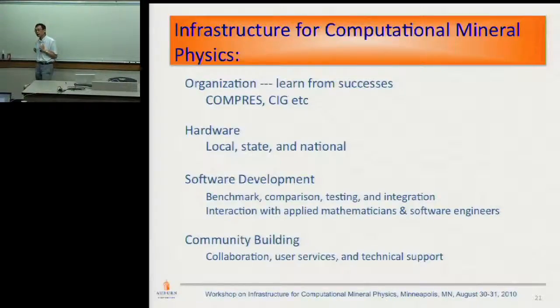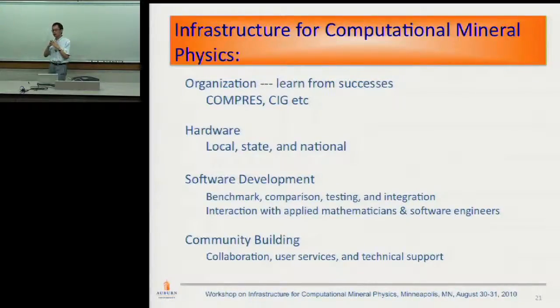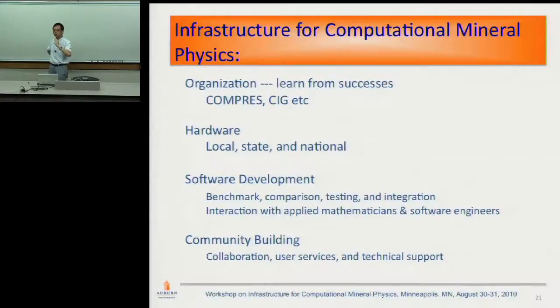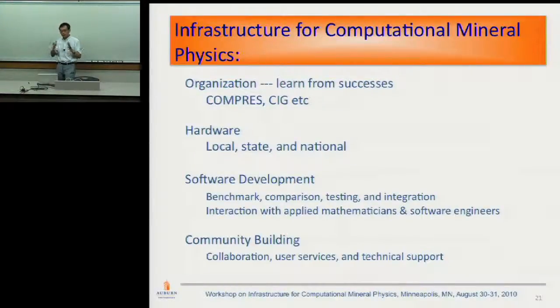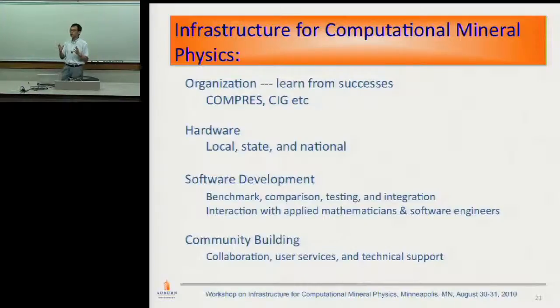We only had one paper on the conductivity of MgO maybe 10 years ago, and this year we actually have three papers. They all work on MgO — one using non-equilibrium molecular dynamics, and another using phonon theory but with equilibrium molecular dynamics to extract the phonon lifetime. That's actually a nice idea: you use molecular dynamics to extract the phonon lifetime. The advantage over the method we use is that they don't do truncation — they account for third order, fourth order, everything.